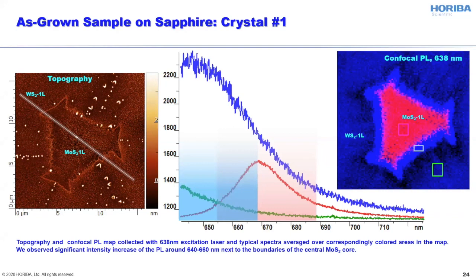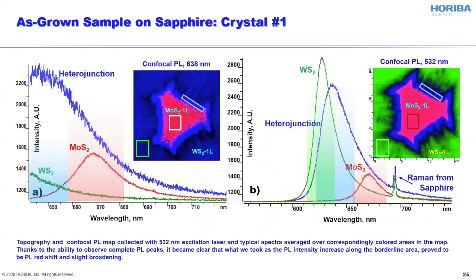This map was collected with a 638 nanometer laser, but when we collected the same map with a green laser, which allows us to see the full PL peak of tungsten disulfide, located at around 630 nanometers, it actually turned out that the transition area has a slightly less intense peak, but quite significantly widened and quite significantly redshifted. So it's a very direct indication that something interesting is going on in the transition area between molybdenum disulfide and